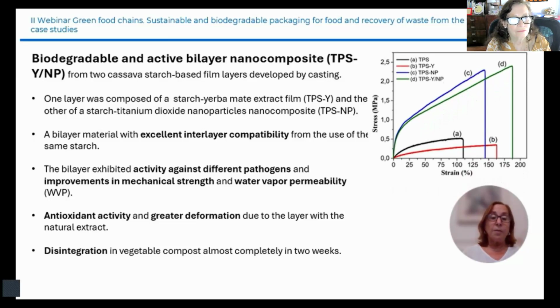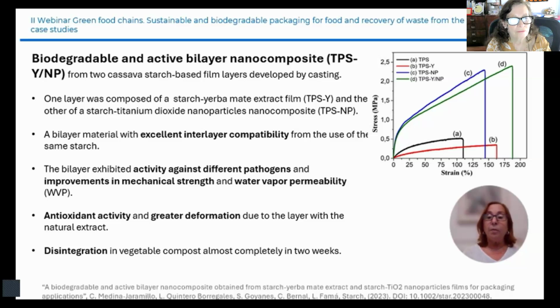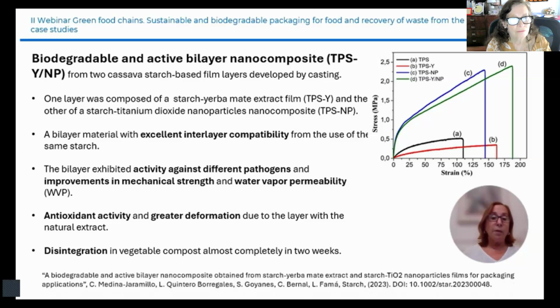The films presented antioxidant activity and greater deformation due to the layer with the natural extracts, as you can see comparing the blue and the green curves, and the disintegration in vegetable compost was almost complete in 2 weeks.